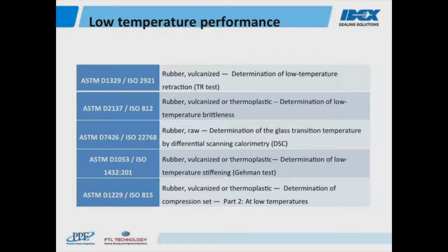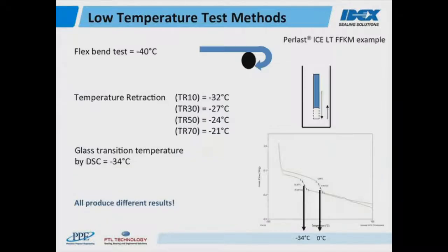As we saw in the previous slide, there are a number of test methods, and as you might expect, they will give different results. As an example, if we tested our Perlast Ice low temperature FFKM, we would find different results. We could, for example, flex the material around a mandrel and it wouldn't break at minus 40 degrees C. The temperature of retraction would have a different number, and the DSC glass transition would be yet another number.